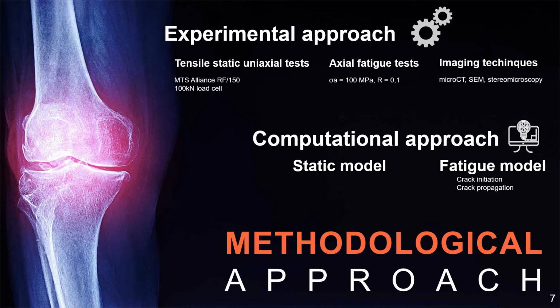Tensile tests are performed instead of compressive tests due to the presence of unmolten titanium powders inside the lacunae caused by the intrinsic property of the laser powder bed fusion fabrication method. Both fatigue tests up to failure and interrupted cyclic tests are performed in order to identify the region where the crack starts and how it propagates. Fracture surfaces are observed by stereomicroscope and by scanning electron microscopy.